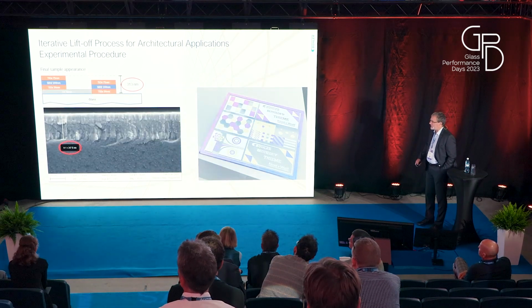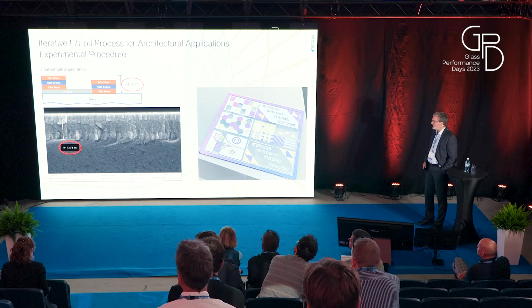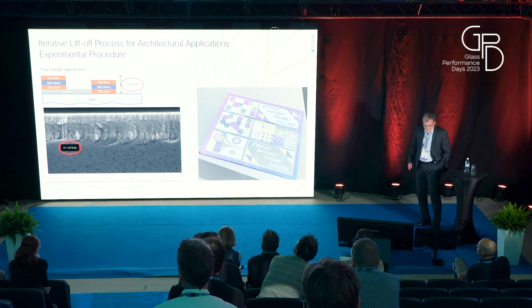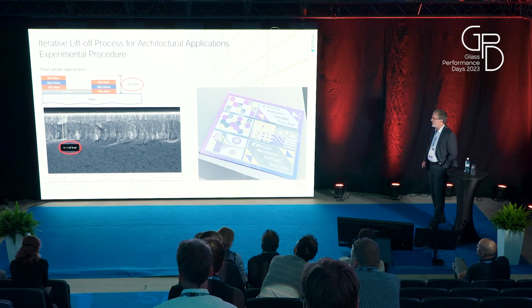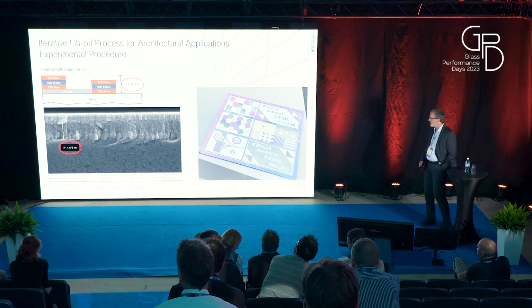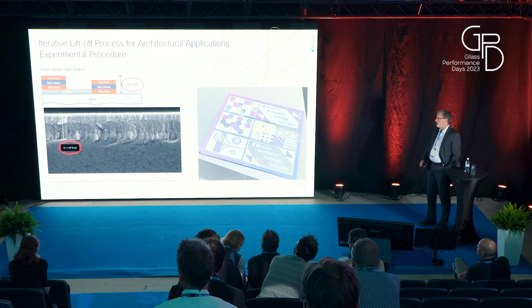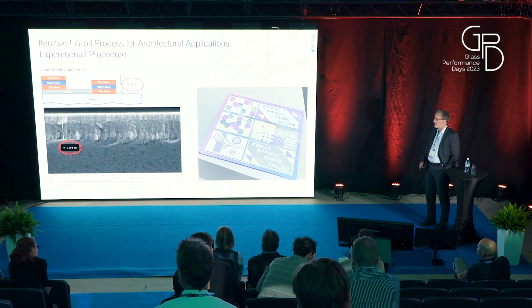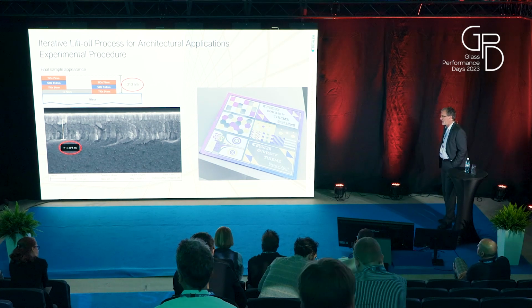Yeah, just some data which came out of the SEM. We could actually also check the coating thickness. So it was something like 370 nanometers measured, and 313 was the design, so coating engineers obviously did a good job. And yeah, this was the process to finalize, to get patterned coatings on a piece of glass with different